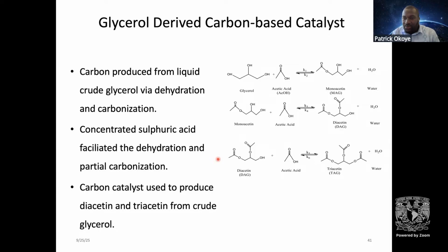So, how did we produce carbon from glycerol? Simply, we added concentrated sulfuric acid, which acts as a dehydrating agent and partially carbonizes this material. Eventually, we had carbon full of sulfonic groups. These sulfonic groups can catalyze the esterification reaction of glycerol with acetic acid to produce triacetin or diacetin. One of the uses of this diacetin and triacetin in biodiesel is that they are fuel additives.